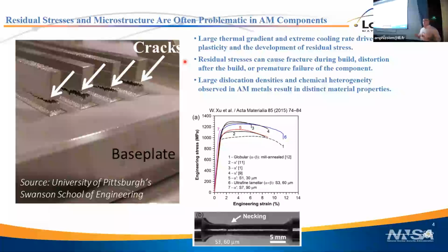So of course, additive manufacture results in different microstructures and different properties, because microstructure, of course, controls properties. You have lots of problems with residual stress in additive manufacture. You can get cracks and fractures as you're building the part. They can happen after the part is completed. But maybe less obvious, it also often results in material properties that are fundamentally different than conventionally manufactured components.